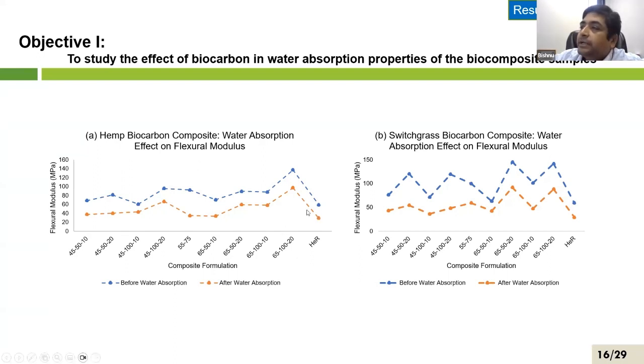But interestingly, for the 20% biochar produced at 650 °C, the properties are still above just the hemp resin composite. So that's definitely not a small amount either. I'm going to eyeball it and say, are you triple or quadruple flexural modulus? Yeah. So we are looking at somewhere 42 versus 80. So it's a double. Okay. Wow. That's very impressive.